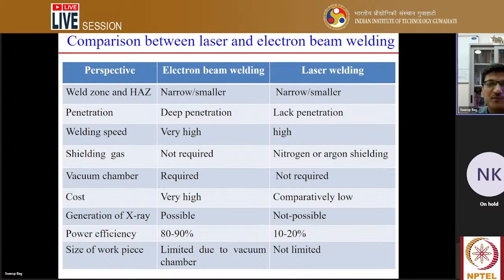Welding speed: a very high speed can be utilized in case of the electron beam welding process. Laser welding is also very high as compared to the arc welding process, but it is less than the electron beam welding process. Shielding gas: electron beam welding occurs under vacuum, so there is no question of contamination of the welded zone. So in that case, there is no requirement of any kind of shielding gas, but in the laser welding process we can utilize different shielding gases. A vacuum chamber is required for the electron beam welding process, but for laser it is not required.